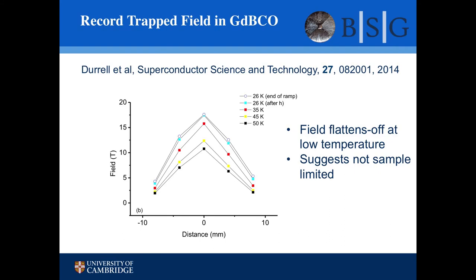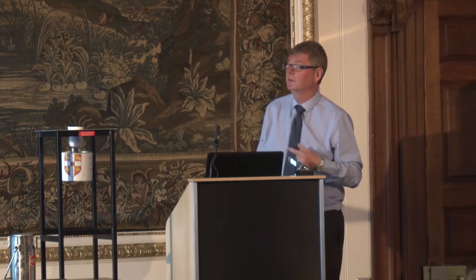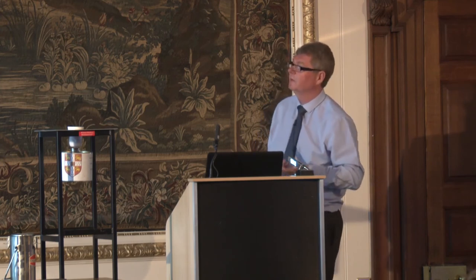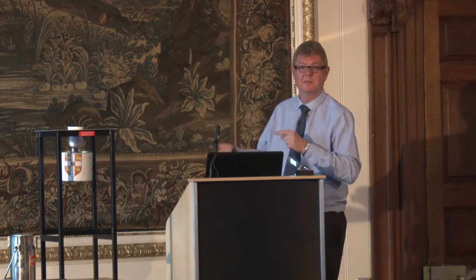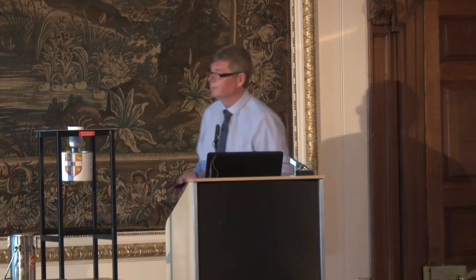And this shows you the field distribution at low temperature, and you can see this is flattening out. So if you extrapolate this, you find that it should go up to about 22 tesla. And right now, John Durrell, with the student Jordan Rush, is over at the National High Magnetic Field Laboratory trying to beat our own record.